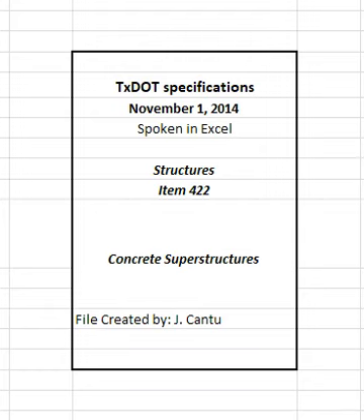Make the check with the straight edge parallel to the center line. Lap each pass half over the preceding pass. Remove all high spots, and fill and float all depressions over 1/16 inches deep with fresh concrete. Continue checking and floating until the surface is true to grade and free of depressions, high spots, voids, or rough spots.